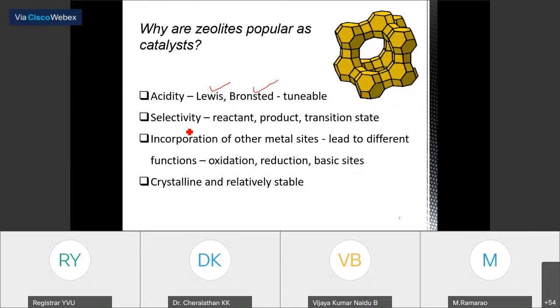And not only that, they show selectivity. They exhibit reactant selectivity, product selectivity, and transition state selectivity. So during a reaction, if you need a product selectively, then you can go for a catalyst like zeolite, because by choosing a particular type of zeolite, you can obtain a particular product selectively. It is possible. And not only that, there is also incorporation of other metal sites.